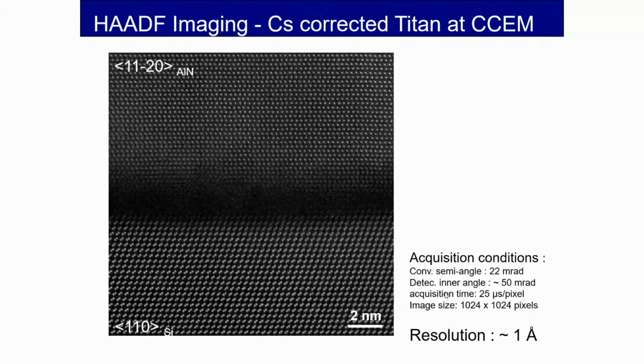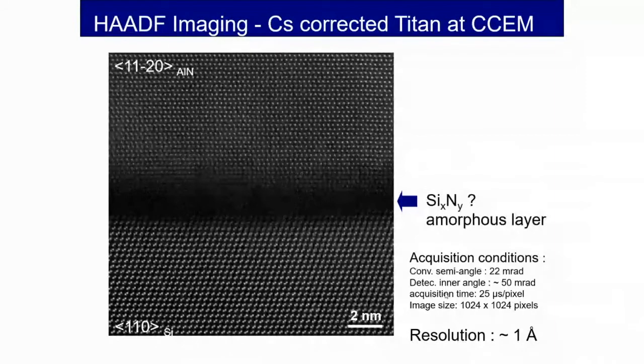And when we took this picture, totally unexpectedly, we didn't expect to see this, in the middle, instead of having a sharp interface between the aluminium nitride and the silicon, you see there's this amorphous layer, which we thought was probably silicon nitride. And in the electron microscope, you can do chemical analysis on an atomic scale, because when you bombard the material with electrons, X-rays are emitted, and those X-rays are fingerprints of the element.